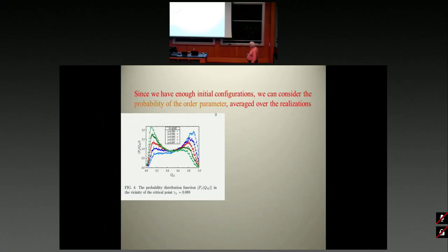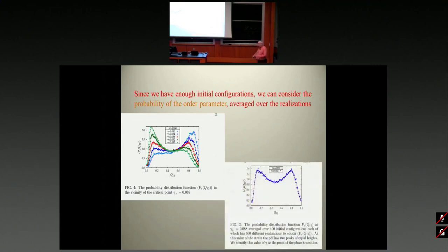When you go beyond the yield, you have a big peak at small q12. Okay, so you have already yielded, and there is a point in the middle where they are sort of at the same height, which you would accept as a first-order transition. So it looks like a phenomenology of a first-order transition. In the thermodynamic limit, you expect that when one maximum is just a little bit smaller than the other, boop, it'll jump there. This is sort of the Maxwell construction. And the phenomenology here, you see within the replica theory, is that of a first-order transition.